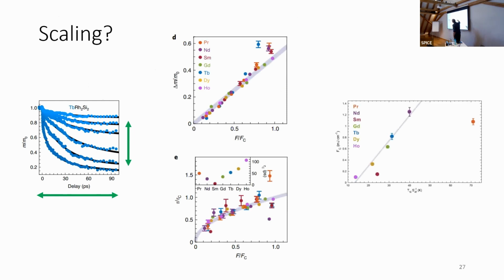Here you have amplitudes as a function of a normalized fluence, which I'll explain in a minute. Same goes for time scales. These are time scales normalized by a characteristic time scale per material. You see that the time scales do vary a lot between the materials. Samarium is the fastest, holmium is the slowest. But they all fall on this one curve, which has meaning, which I will not explain because that's difficult for me to explain, but this is a square root.